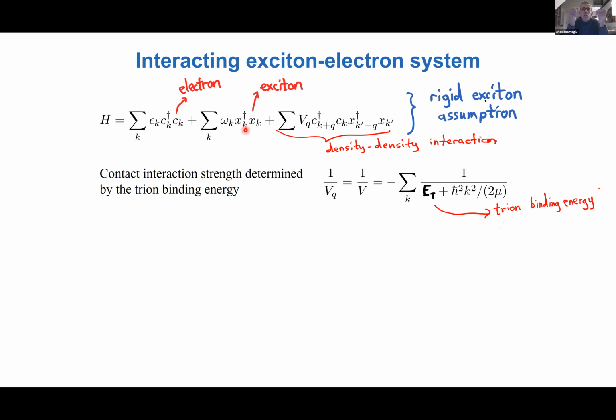The electron and exciton interact because the exciton is a polarizable object and the electron is charged, so the resulting interaction is attractive and goes as 1 over r to the 4. So it's a relatively short-range interaction, and it's a density-density interaction, so we can write it essentially as the exciton density times the electron density. Because it's short-range, we can express the interaction as an effective contact interaction. This contact interaction strength would be given by the trion binding energy associated with the interaction potential. And of course, we need to regularize it by introducing a cutoff.